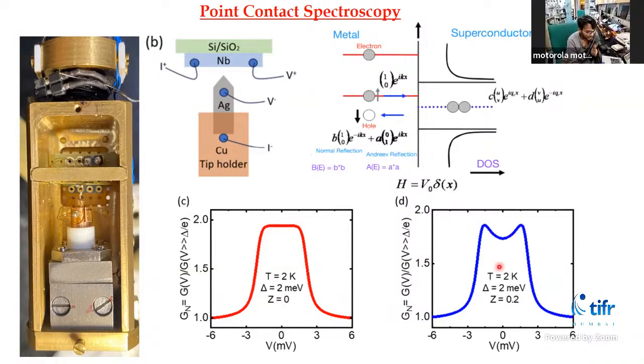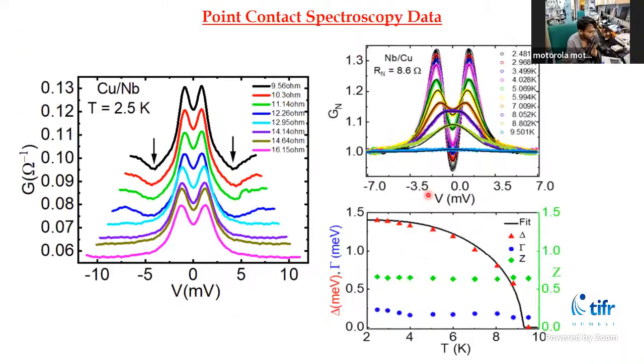So this is real data I am showing here. When a junction is formed, it can give many kinds of spectra. I'm showing you how the spectra evolve for different resistances. Here is a spectrum that is not that good, as we are getting some effect of critical current. But when we go to some higher resistance, we can establish a ballistic regime contact, which can give us some information about the superconducting density of states and its gaps.